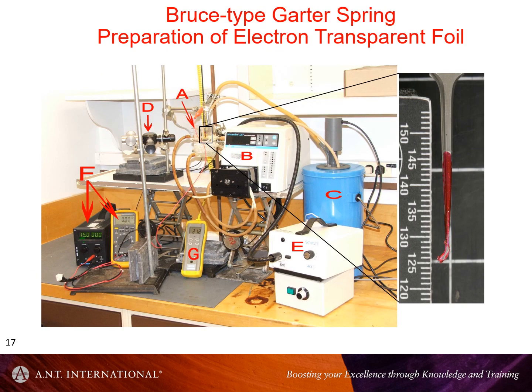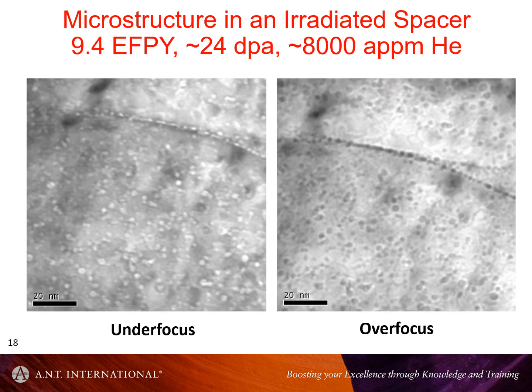So one of the things that I did as a program manager at Chalk River, I said, well, we must do some TEM. We didn't have any sophisticated FIBs at the time, but we did have some electropolishing equipment. And we have very good technicians, and they were able to build a little twin jet electropolishing setup here to polish these 1 millimeter wide sections of the spacer. I mention this because I was in my office one day when the guys had prepared the samples, and they called me over because they said, what you thought you would see, we don't see it.